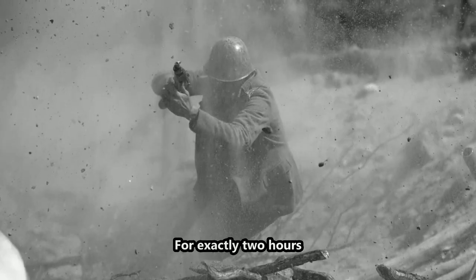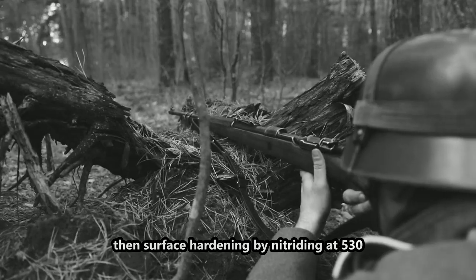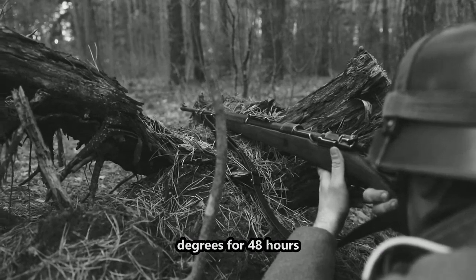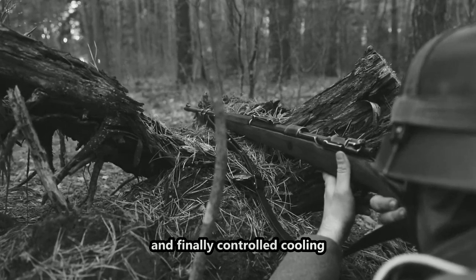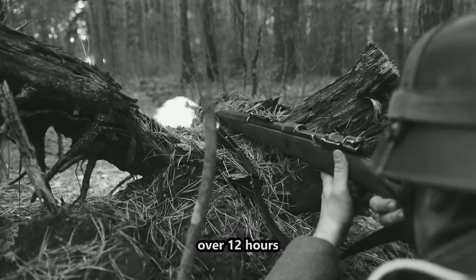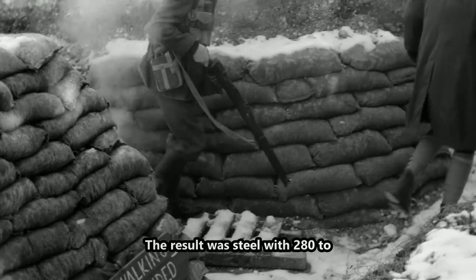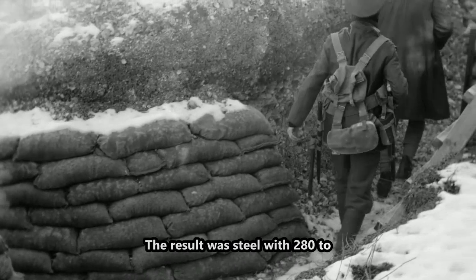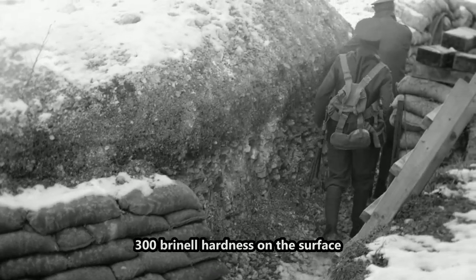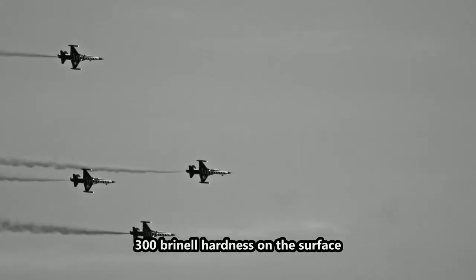for exactly 2 hours, then surface hardening by nitriding at 530 degrees for 48 hours, and finally controlled cooling over 12 hours. The result was steel with 280 to 300 Brinell hardness on the surface, 240 Brinell in the core.